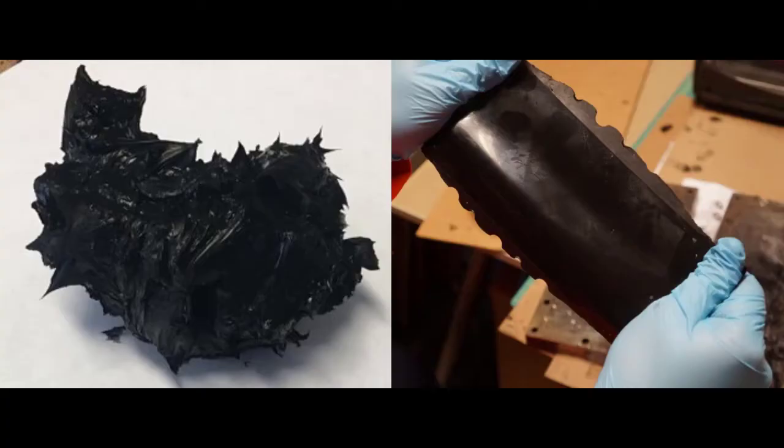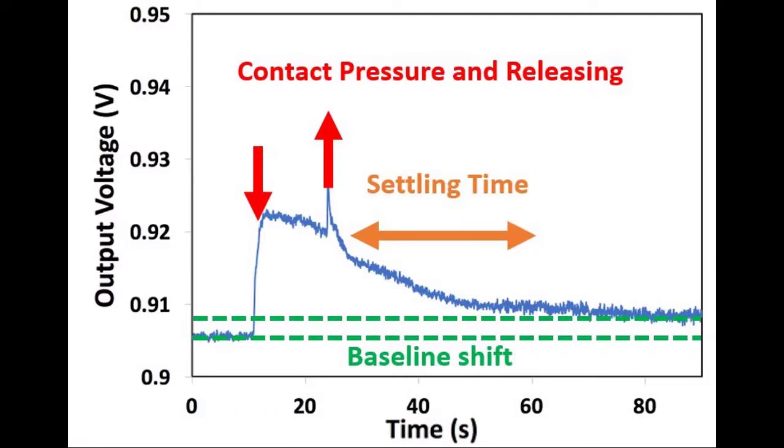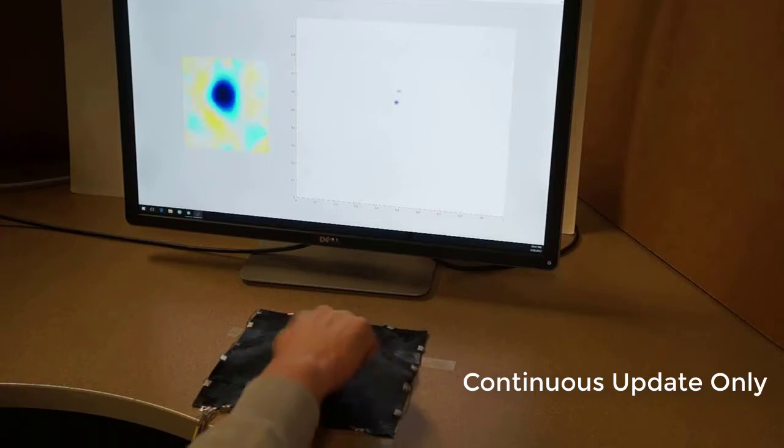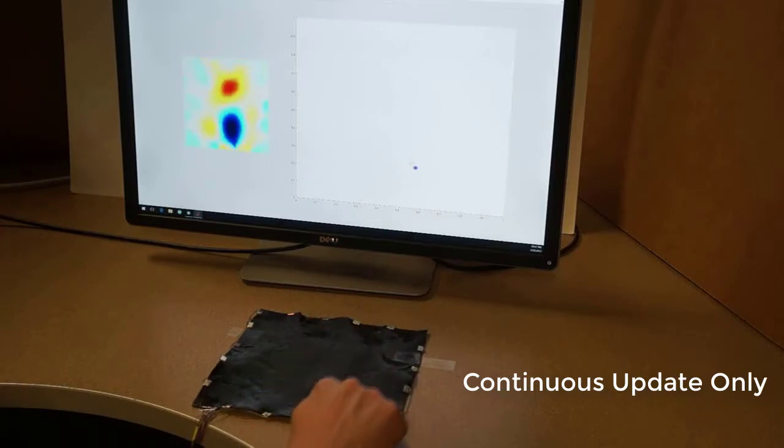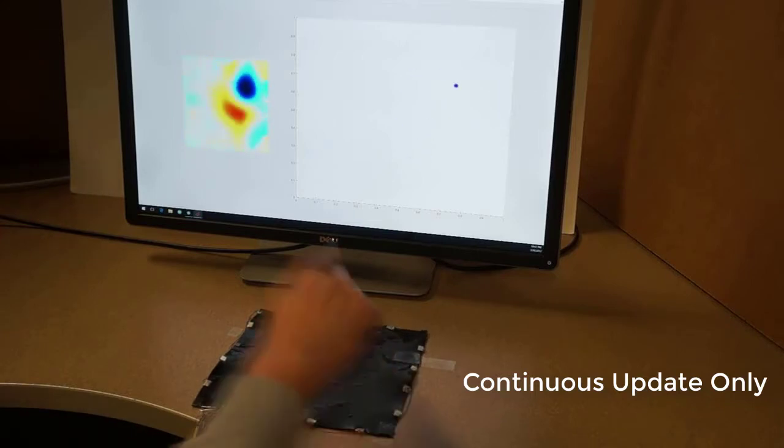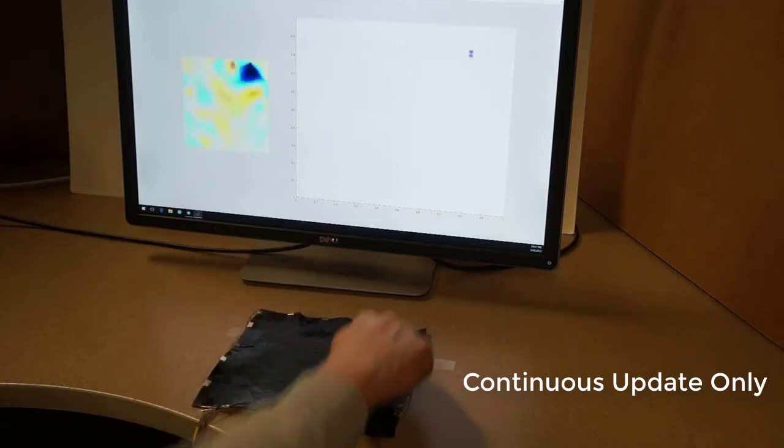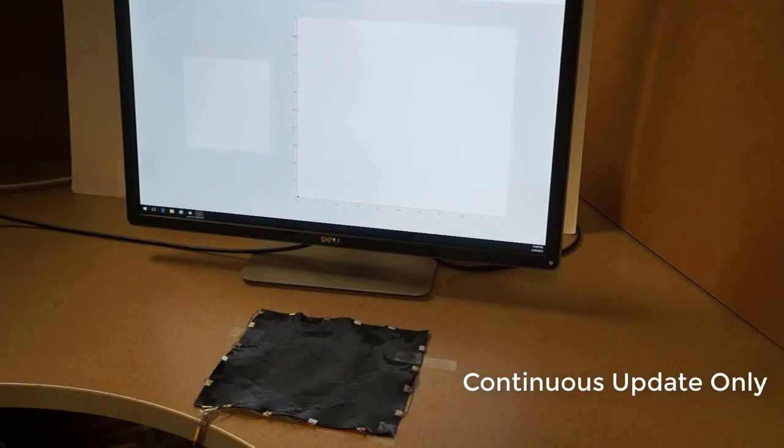Carbon-filled elastomer is known for its piezoresistivity. However, it requires a long settling time after excitation, and the small shifts in baseline values make it hard to use for real-time input devices. Fast EIT method can compensate these issues by refreshing the baseline values every frame.